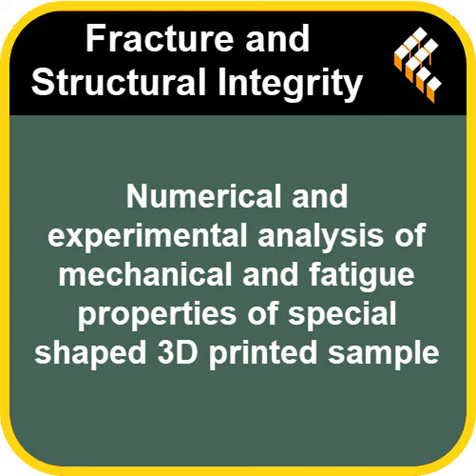Right. And second, this combined approach, taking experimental results, using inverse analysis to calibrate a numerical model, and then running fatigue simulations, it's a proven, validated methodology. It works for accurately predicting service life and, just as importantly, highlighting the critical weak points where a design needs improvement. So wrapping this up, what does this all mean for us or for you listening? We've seen that inverse analysis can successfully calibrate these numerical models. It makes them reliable tools for understanding the really complex mechanical behavior of FDM 3D printed parts. It's potentially a valuable shortcut to engineering confidence, saving time and money compared to endless physical prototypes.